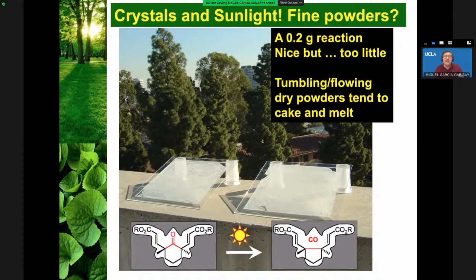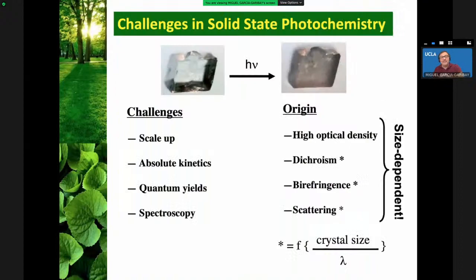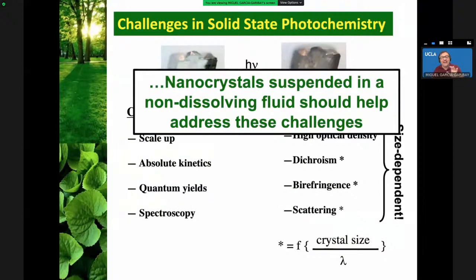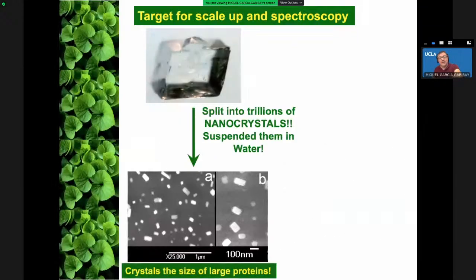If we were to use dry powders in a tumbling or flowing apparatus, it wouldn't work. They will tend to cake and eventually melt. So what we came up with is a different solution, which is nanocrystals. Prepare nanocrystals suspended in a non-dissolving fluid. That should help address these challenges.